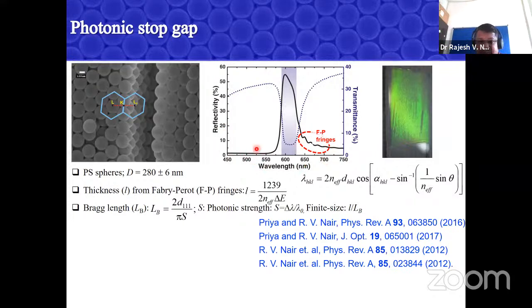on the sample. So you see there is a peak in reflection at some wavelength, which is around 600 nanometer. And in parallel, I also measure the transmission of light through the sample. If you look at the transmission, it starts with high transmission at a high wavelength, and as I decrease the wavelength, the transmission reduces, and it reaches a minimum value where I get the maximum value in the reflection. So you have a system, a piece of glass or sample with you. You send all these light of different wavelengths, and certain frequencies or certain wavelengths centered around 600 nanometer cannot propagate. And the light which is absent in transmission is not absorbed, it's completely reflected back.